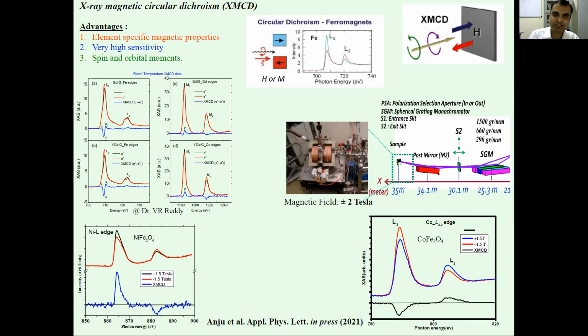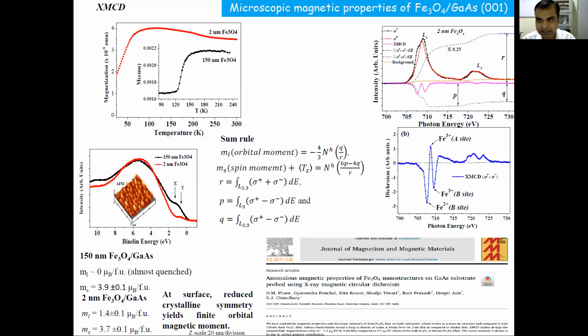And here is one such example, Fe3O4 again. So why is this important? Because Fe3O4, as I discussed yesterday, can be comprised of FeO plus Fe2O3, number one. So we have 1 iron in 2 plus and 2 iron in 3 plus. And importantly, in Fe3O4, there are two sites, the tetrahedral site and the octahedral site.